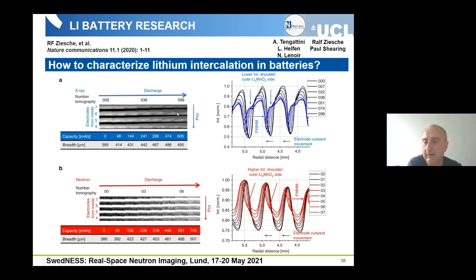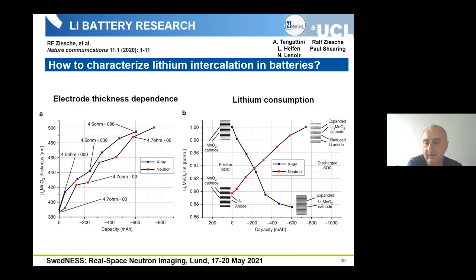the electrode is expanding, and we have some intercalation of lithium in the electrode. This can be studied also with X-rays and neutrons. So you see here how the thickness of the electrode changes with the capacity. And here, this is the contrast related to the lithium consumption with X-rays and neutrons. So we have complementary contrast.